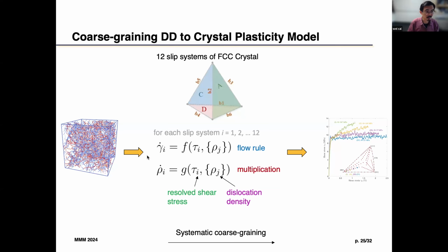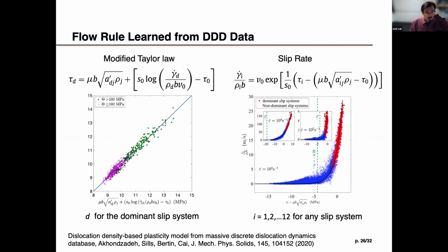The question is, where does the function f, which is the flow rule, and the function g, the multiplication, come from? But if we can learn that from the DD data, then that's a more systematic way of doing it, right? So I will go through some of the things very quickly. One thing is that my former student Hamed looked at all this data, and this is the best he can find. So this is a pair relationship: the flow stress as a function of gamma dot, and if you invert it, gamma dot as a function of applied stress. That I would say is reasonably supported by the DD simulation, and he compared different functional forms, and this is the best he can get.